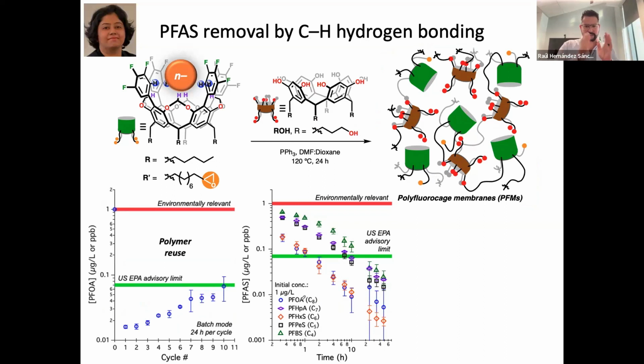Anyhow, we tested how many times we can reuse our polymer. This is essentially just taking the same polymer and bringing the concentration of PFOA back to 1 ppb, right? So after each cycle, you go back and then we remove, and then we go back and then we remove. And the data tells us that we can use it about 9 times. After that, we go above the advisory limit set by the EPA of 70 ppt.